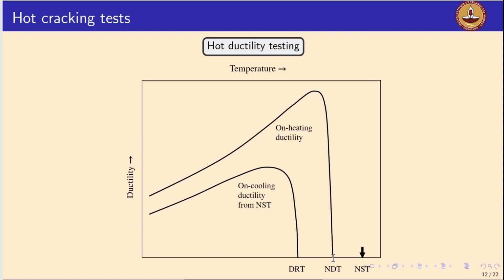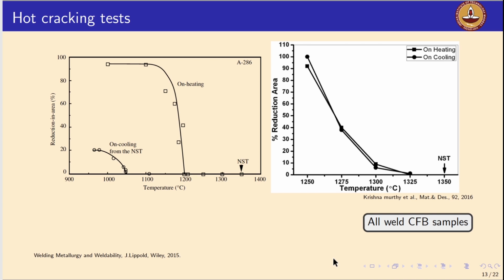So once we identify the candidate chemistries, we carry out extensive hot cracking tests using Gleeble hot ductility testing, right? Then we can optimize the chemistries based on these hot cracking susceptibility tests. So I'm showing such an optimization. The left side figure shows the detailed signatures of an austenitic filler, A286, which I borrowed from Professor John Lippold's book, right? This is one of the fillers commonly used to weld carbide-free bainite. And if you look at the hot cracking susceptibility from this Gleeble ductility testing, the difference between the NDT, NST, and DRT is huge. So therefore, this material can be highly susceptible to hot cracking.